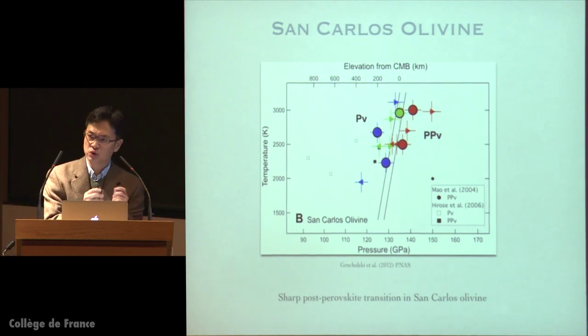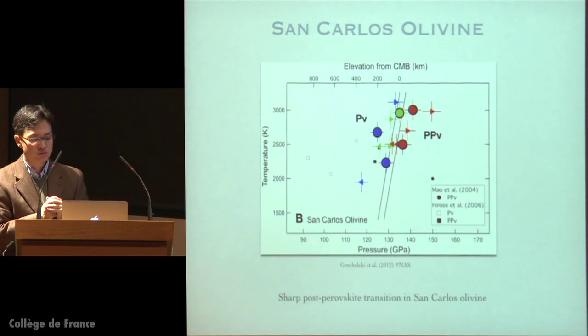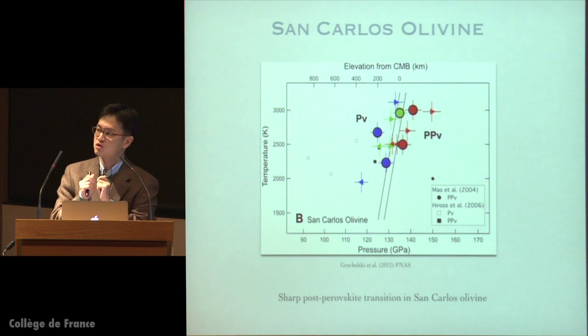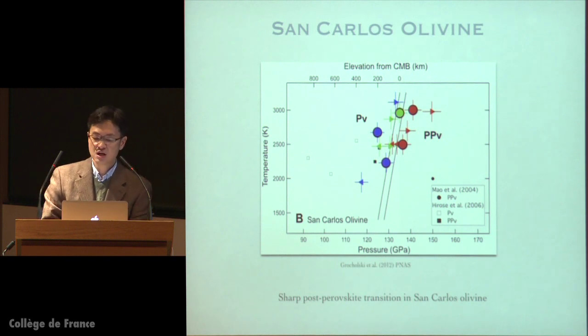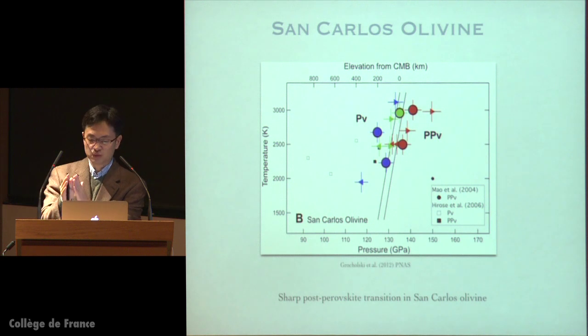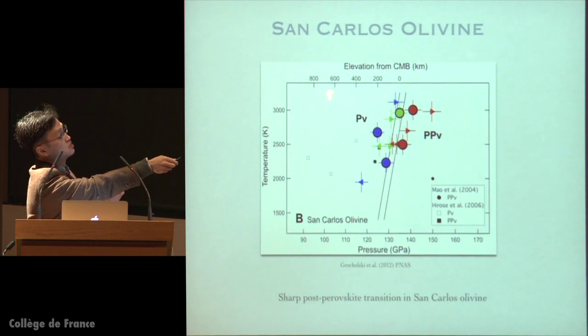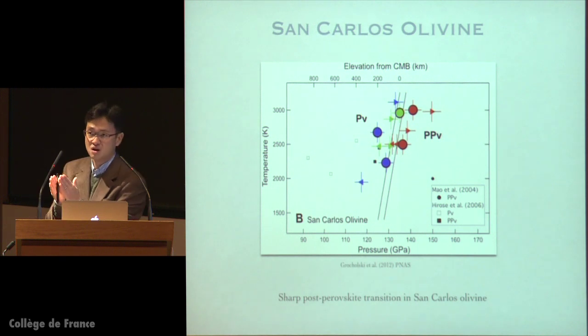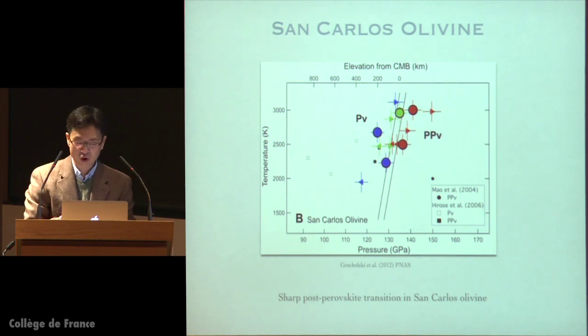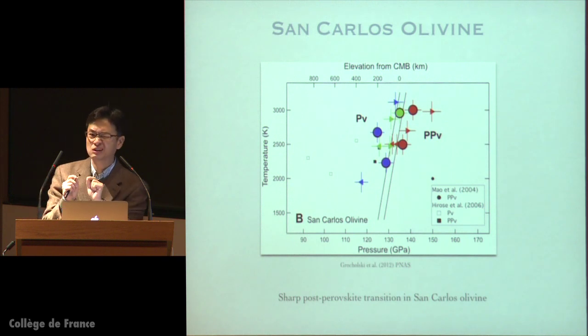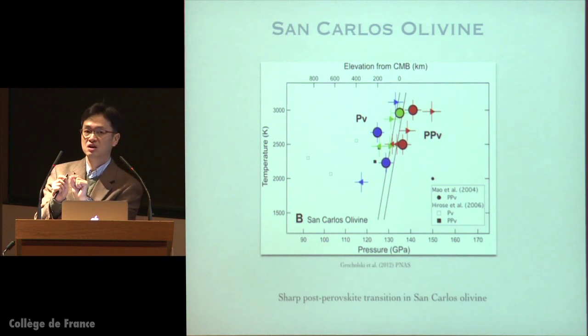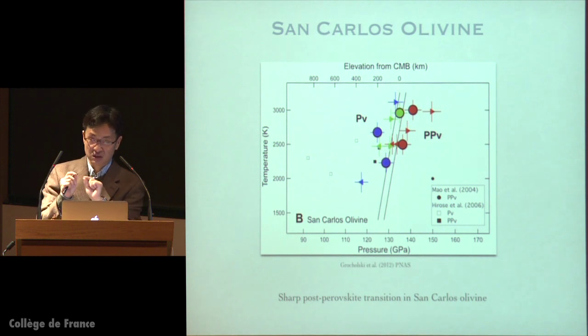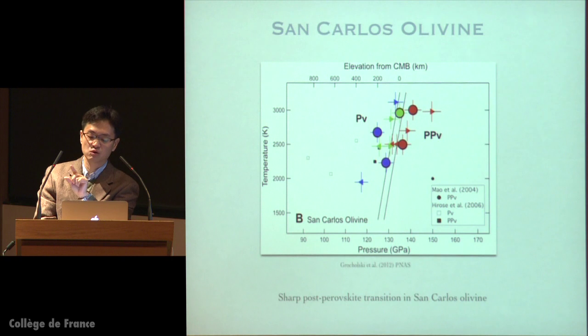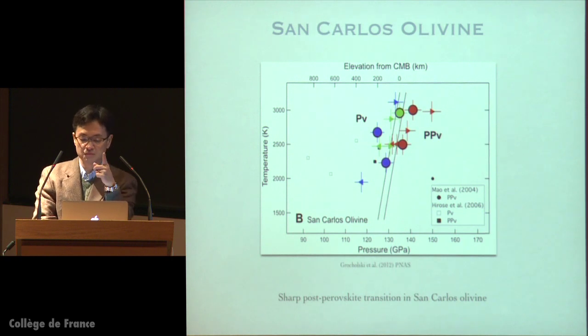You can see some mismatches between two groups of data, but they both seem to agree that the thickness should be fairly small in San Carlos olivine composition. Just to remind you, what we observed in 2009 was 400 to 600 kilometers of thickness. That is about this distance from 0 and 600 here. So this thickness is really narrow compared to what we have observed in 2009. So this clearly indicates that ferropericlase has an impact on the thickening effect of iron. So it effectively regulates the iron effect through element partitioning.